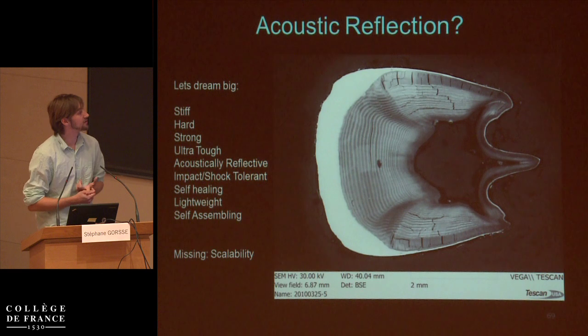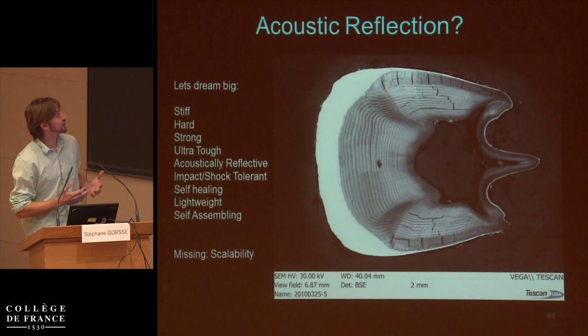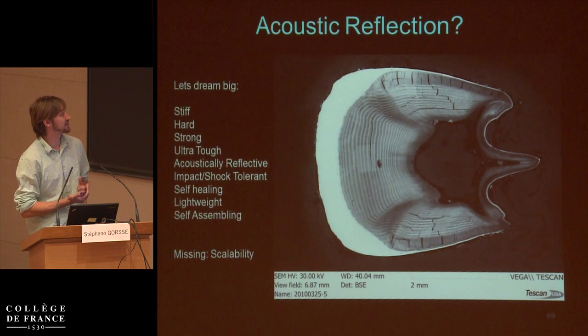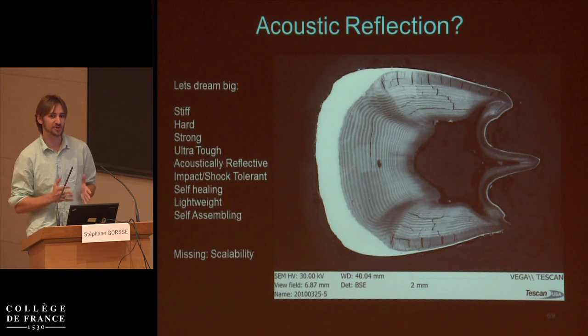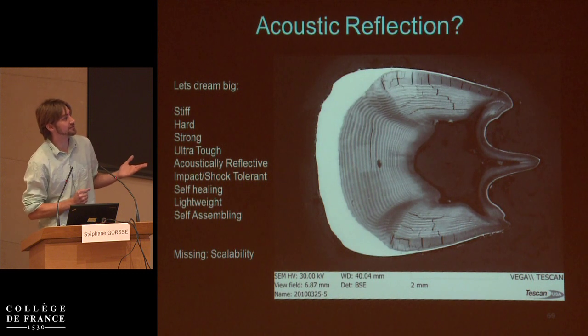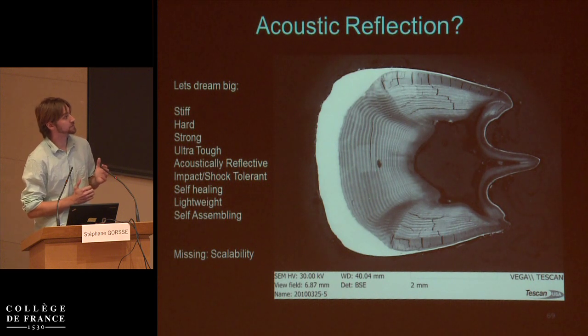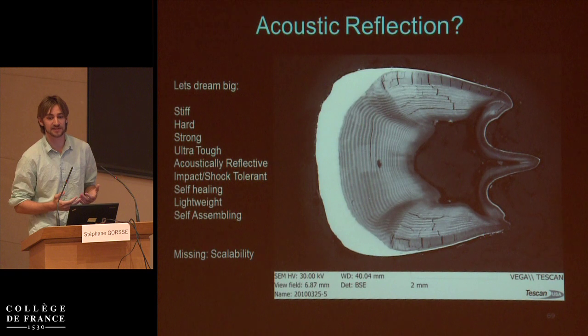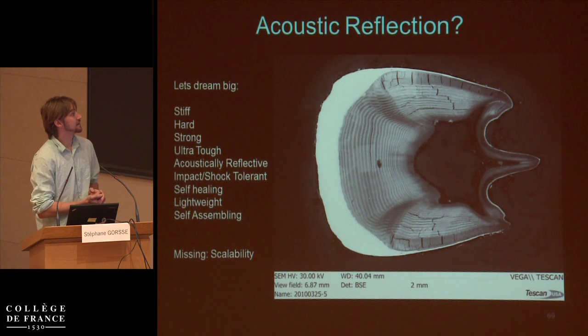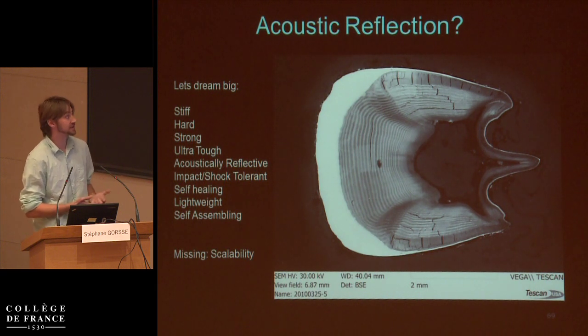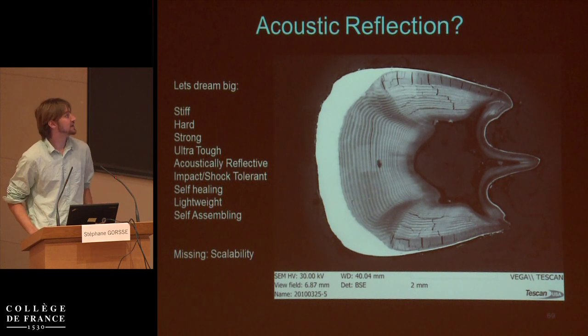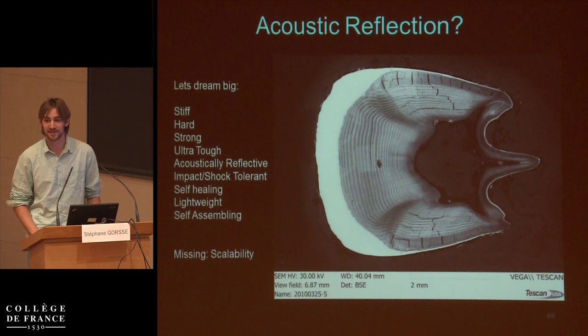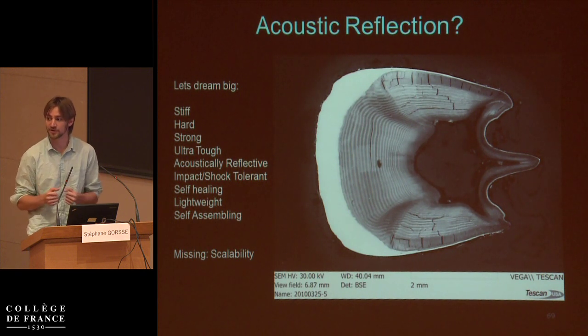And so in the same structural motif, we have something that's stiff, hard, ultra tough, acoustically reflective, impact and shock tolerant. We can't say for sure if the organism is taking advantage of this acoustic reflection phenomenon, but we could certainly imagine creating a material like this and taking advantage of it ourselves. And if we did so, this material architecture would certainly be compatible with the mechanisms for self-healing that we're aware of. It could be lightweight, and cholesteric liquid crystals self-assemble. So really the only thing it's missing is scalability, and that's simply because you're constrained in how far you can separate your pores.